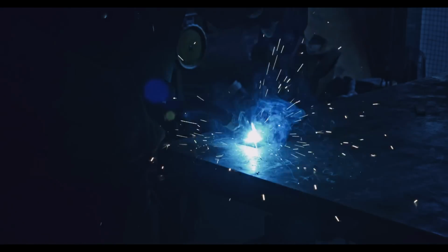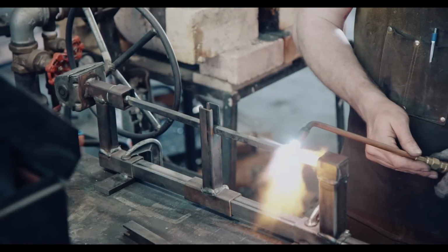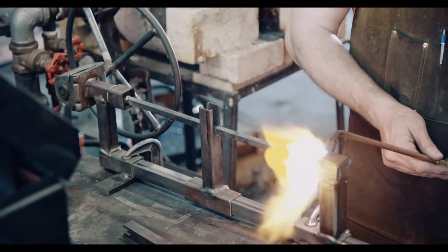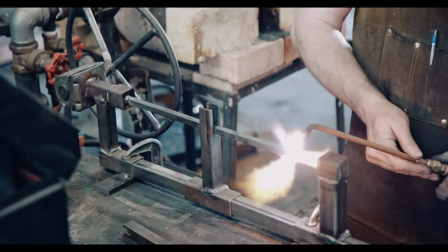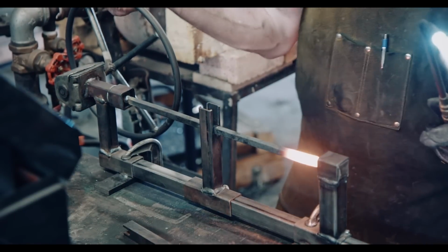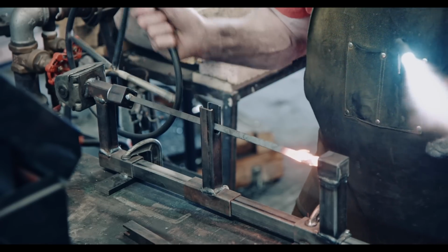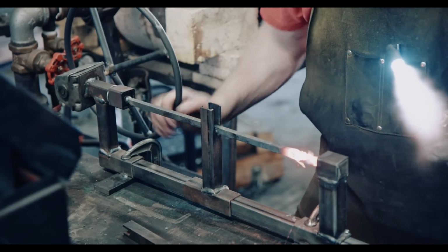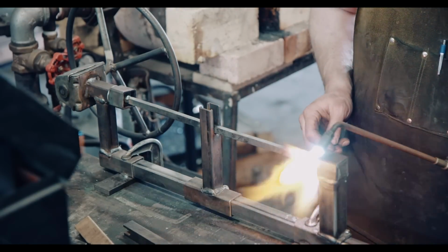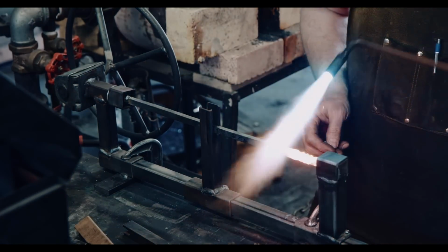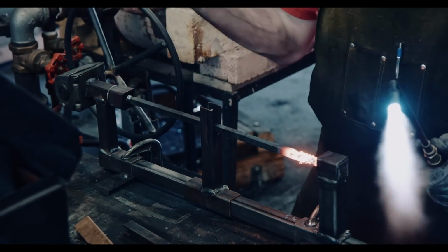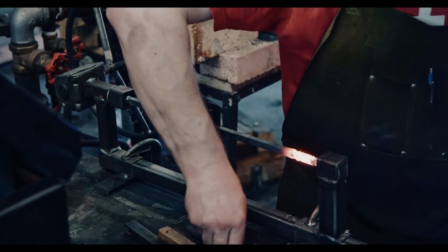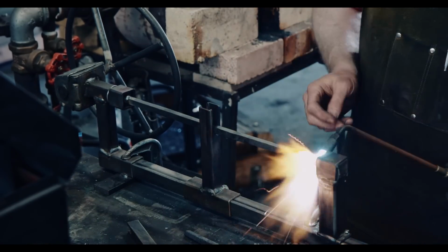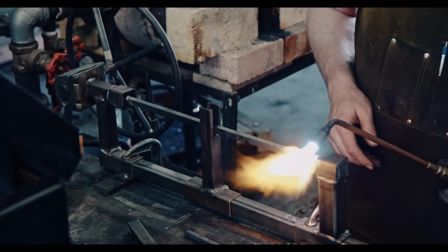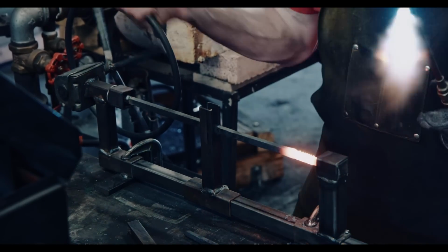Once the bar is in the twisting jig, I'm using the oxyacetylene torch to heat the bar to a bright orange and then slowly twist it. My method is to heat up roughly 2 inches of bar and then make a constant number of twists so that the pattern stays even throughout the whole bar. To prevent the bars from shearing in the corners, I usually put on a slight chamfer to reduce the transition angle. With the jig and the torch, twisting is usually a fairly quick process and becomes very repeatable.